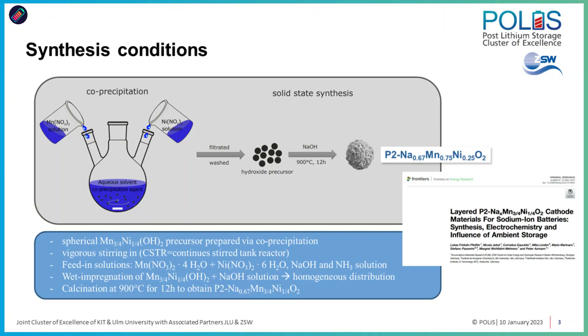For synthesis we use a coprecipitation method. This is a method normally used in industry to develop cathode materials at the ton scale, so it's a method which is available for scaling up. Our focus at ZSW is always to look at how to scale up materials and cells, so we adopted this strategy for synthesis, looking already at producing materials in the kilogram scale. This was the synthesis of the material; the doping was done following the coprecipitation followed by the heat treatment.